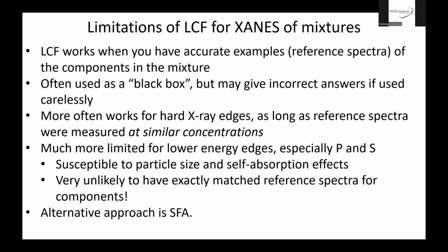Now, at lower energies for phosphorus and sulfur, it's even more complicated, because self-absorption is prevalent and it's particle size related, it's always there and it's always variable. So it's almost impossible to have exactly matched reference spectra. And the unfortunate thing about linear combination fitting is that peak height will dominate the fit. And so it's easy to fool it and get the wrong answer. So an alternative approach is SFA.